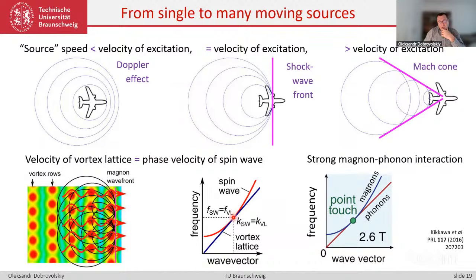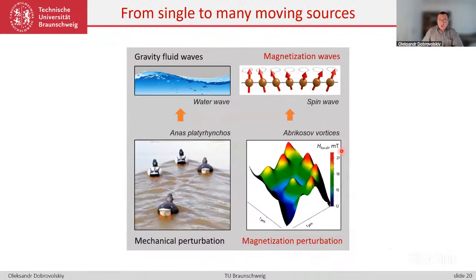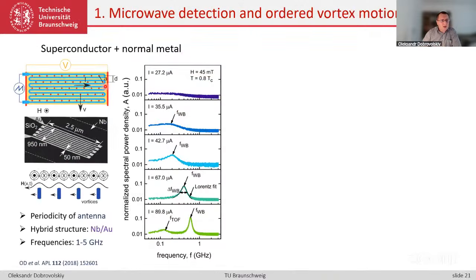And this type of interaction, having a crossing or touching point for two dispersion characteristics, was already investigated, for instance, for the interaction of magnons and phonons in a different physics context. But in contradistinction to ordered systems, vortices, as shown here as ducks, should actually be properly located. If some vortex is located improperly, there will be destructive interference, so care should be taken regarding the long-range order, like perfect crystallinity, for the moving vortex lattice. So the first thing to check is whether we are able to detect microwave excitation from vortices or spin waves with high enough sensitivity, and whether vortices can move in a coherent fashion.